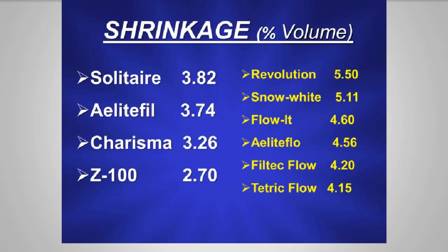And the thing I might ask you, if we look at these composites here on the left, which of these composites, if we go ahead and place it, let's say we've used Z100 in a Class 1 composite restoration, we put it in there, we polymerize it, and we take an identical Class 1 restoration and we put Solitaire in there and we polymerize that using the same light at the same energy, and both of those materials shrink, which one do you think induces more stress at the adhesive interface? Well, most people would say Solitaire because it shrinks the most, where in fact the answer is Z100, and it's not even close.